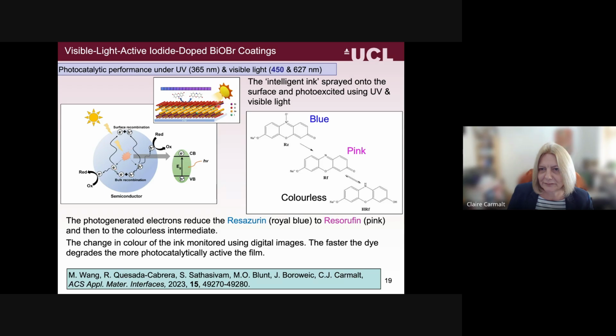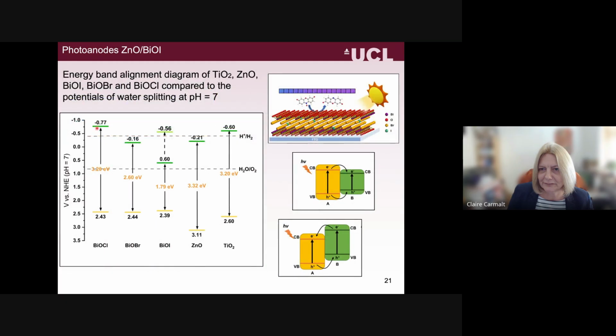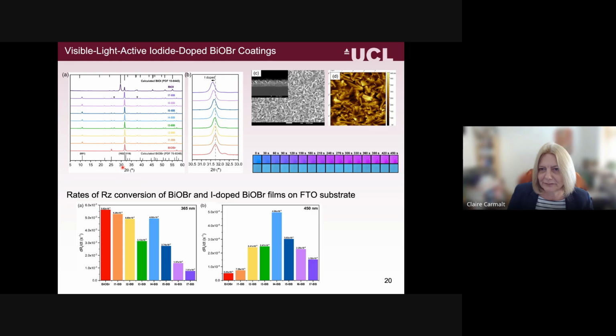So what we were interested in was to look at the bismuth oxybromide, but doping it with iodine, and that's because, it's on the next slide actually. When you look at the band gap, the bismuth oxychloride's band gap is too large, so it doesn't really show any photocatalytic activity. The bismuth oxybromide shows good photocatalytic activity, but it's quite limited in the visible region. And the bismuth oxyiodide, sorry, you can end up getting electron hole recombination. So if we could get somewhere between the two of these, that could be a very effective photocatalyst.